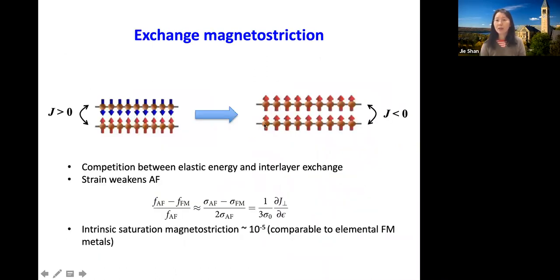And we understand this effect well, because in this case, we have a competition between elastic energy and interlayer exchange. And the balance between the two will tell us the built-in stress for two different magnetic states. And that gives us a difference in the mechanical vibration frequency. So this is very well understood. And for multi-layers, the effect is bigger because you have a larger exchange interaction, because you have more layers.